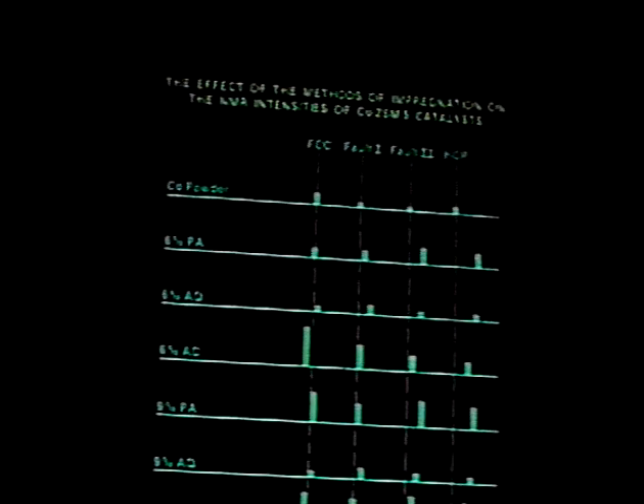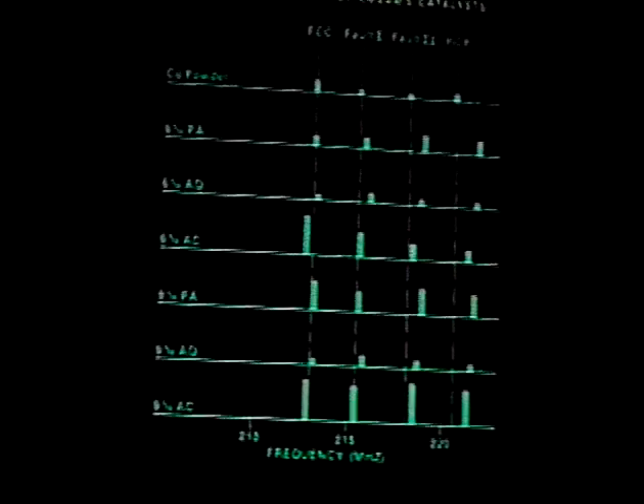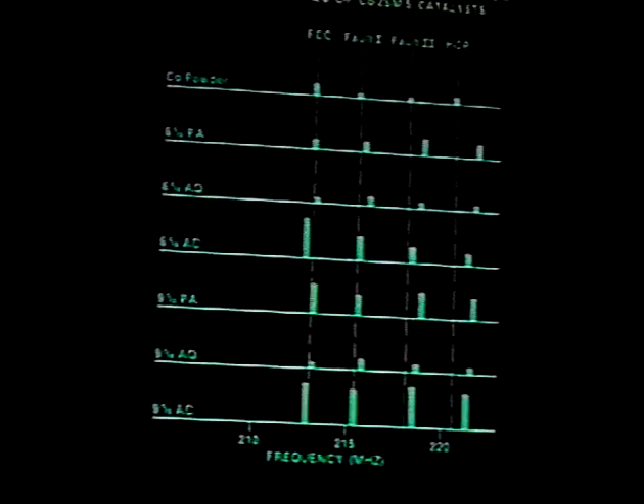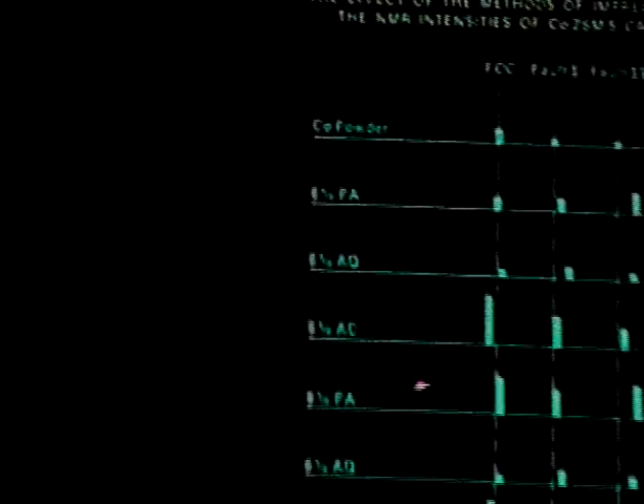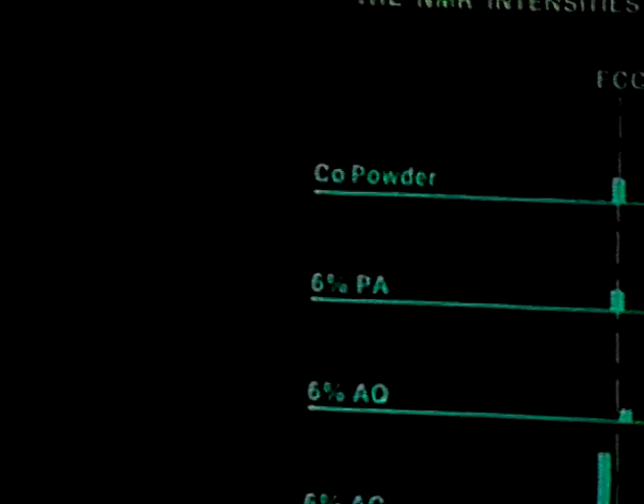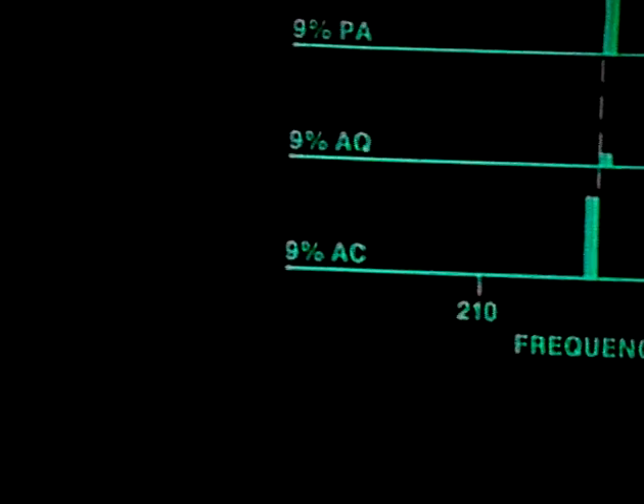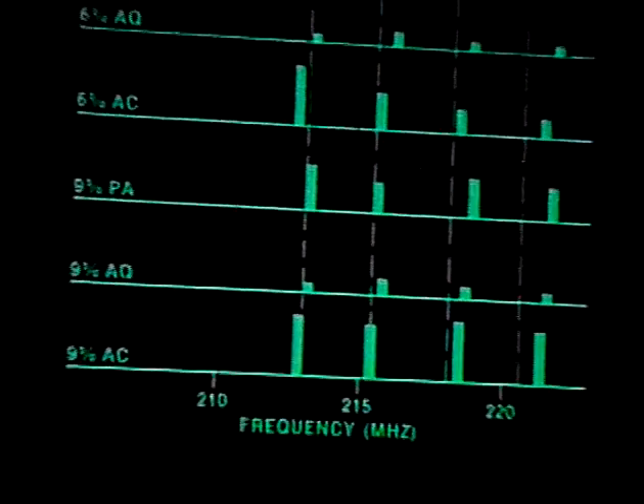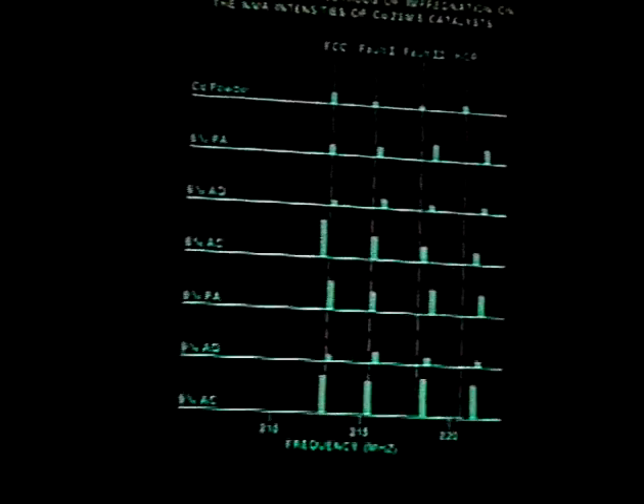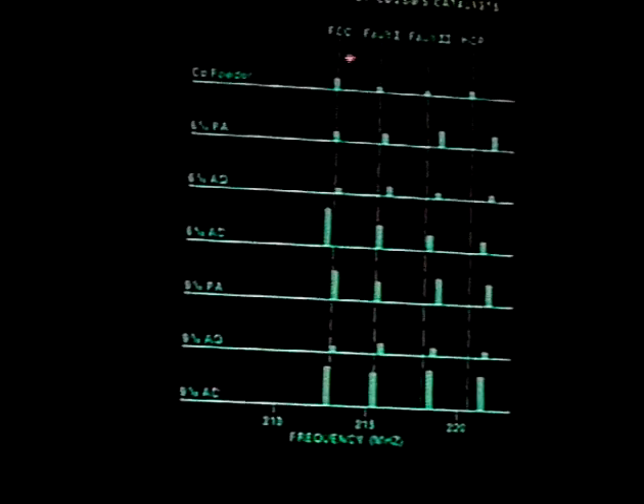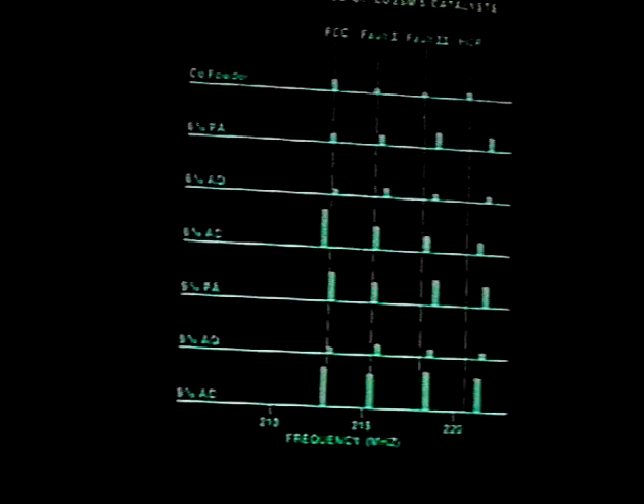Again, we also studied cobalt ZSM5 catalysts with cobalt impregnated on ZSM5 instead of being physically admixed. Cobalt was added in two different forms, the aqueous impregnated and the acetone impregnated samples. And again, all these gave line positions that were found in the cobalt powder with both the FCC and the HCP and the fault lines appearing.